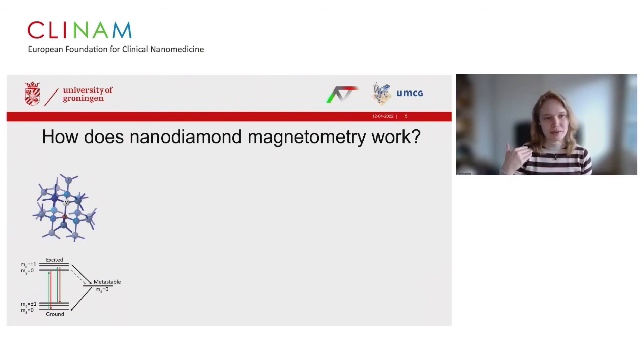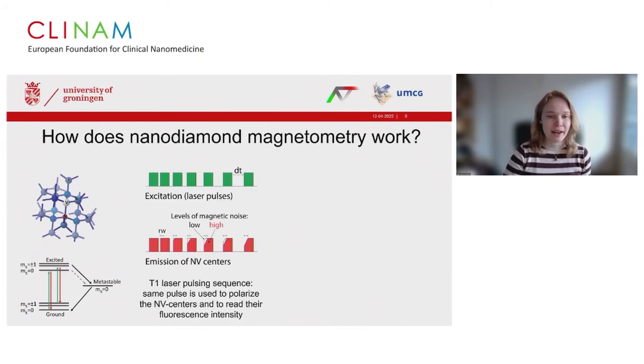We can use the laser pulse to prime the nanodiamond to make its fluorescence as high as possible. And then if we give the particle a certain time to relax, this whole quantum system to relax, then the fluorescence will return to a less bright state. This is exactly what we're doing. So we are pumping the nanodiamonds into a very bright state and then give them a little bit of time to relax and measure their fluorescence.